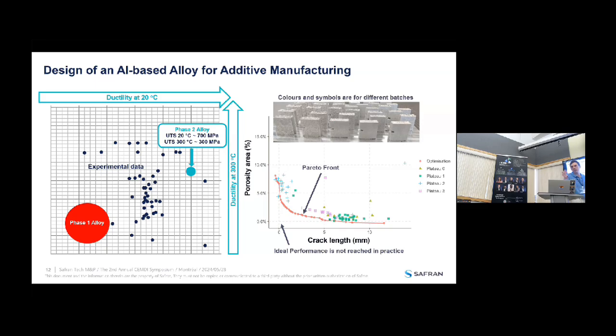Then, you can see that the use of the model led us to the opposite. So we're fine in terms of crack length, but we're not fine in terms of porosity. So we added this data onto the whole data set. We did the optimization and found these points that lie at the inflection points of the curve. And actually, when we included that in the new models and did multi-objective optimization, we found this Pareto front, and I think we arrived about here without finding an ideal solution.